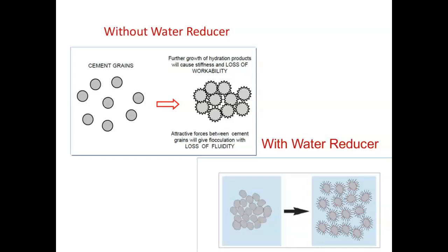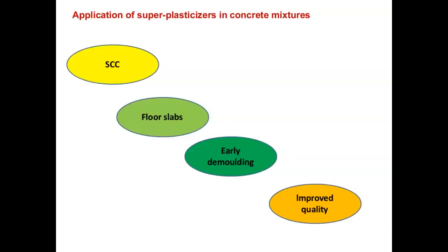One engineer asked me that for M20 concrete he has used superplasticizer. Whether it is necessary to use this water reducing admixture for M20 grade concrete, we have to check. Because for M20 concrete we usually have a water cement ratio of 0.5, which is sufficient for getting workability of the concrete. Once you go for higher grade of concrete, then you have to reduce the water cement ratio. In such a case, to improve the workability you go for superplasticizer. Another thing, for self-compacting concrete or high flowable concrete, you need to go with superplasticizer with less water to achieve the strength as well as workability. But without knowing the proper things, without being given the proper input about the superplasticizer, they just try to add it like that.